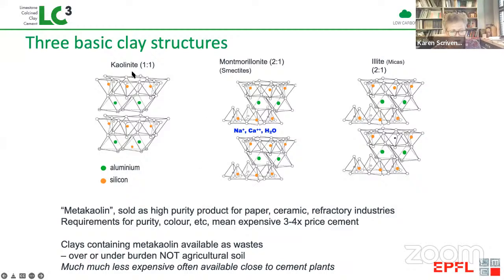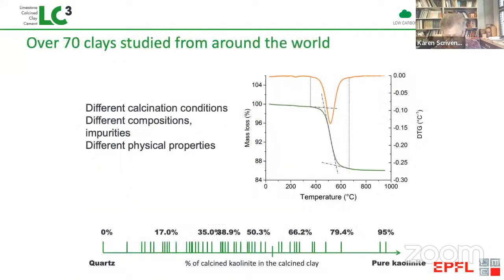And what we want is to have at least some of this mineral kaolinite. This kaolinite has what's called a 1-to-1 structure with 1 layer of silica and 1 layer of alumina. And this means when it's heated in the range 800 degrees, both the silica and alumina are available for reaction. And it's very important to stress that we don't need to have very high purity metakaolin. We certainly don't want to have material from agriculture regions. This is not at all suitable, but there are many, many kinds of clays available which can be suitable.